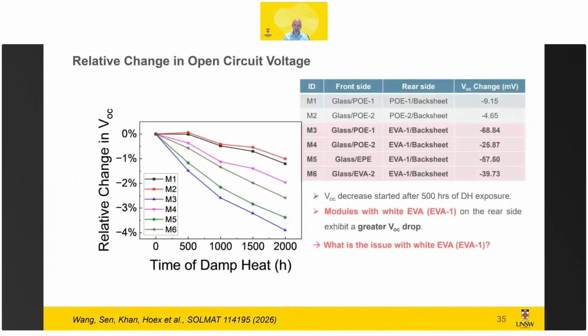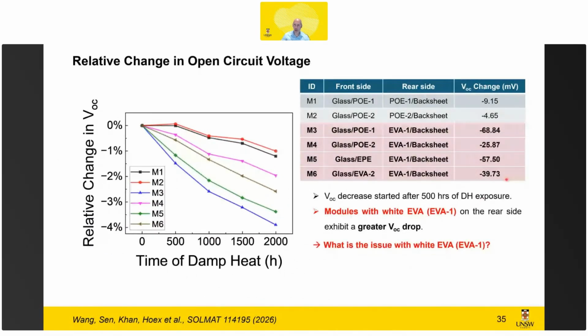And 4% doesn't sound like a lot, but if you then look at how much that is in voltage, in the worst performing case, that's 60 millivolts. So that's of course significant. And that was a 4-cell module, and that was in particular for one type of BOM, white EVA, which had a significant drop in VOC.